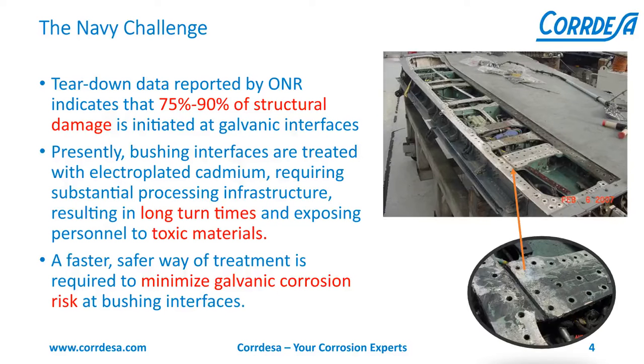The Navy Challenge. With the carbon fiber composite panel removed, the photograph on the right shows a widespread corrosion around fastener holes on the airframe structure of an FA-18. From a number of such teardown inspections, the Office of Naval Research has learned that 75 to 90% of structural damage is actually initiated at galvanic interfaces.